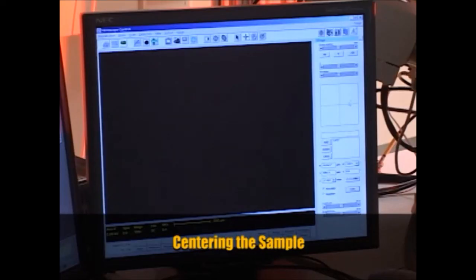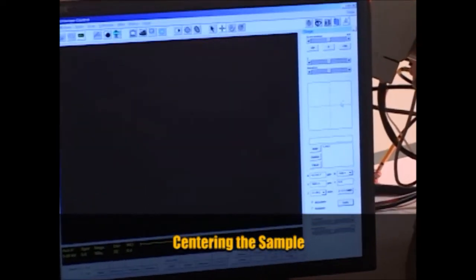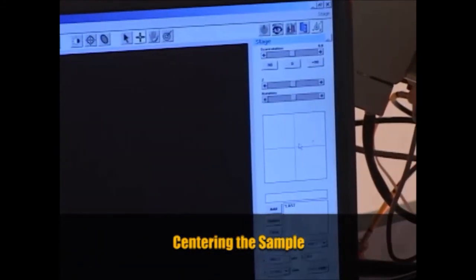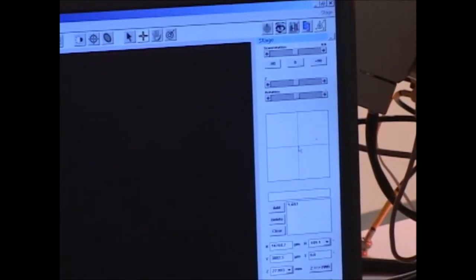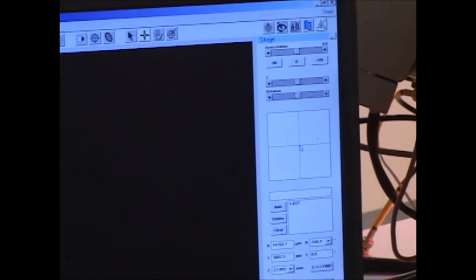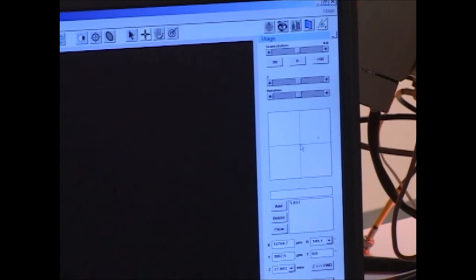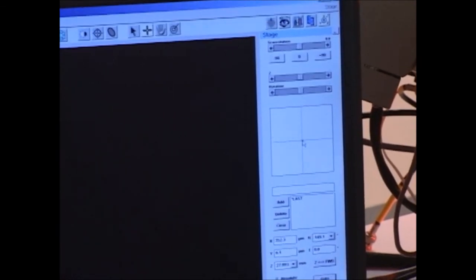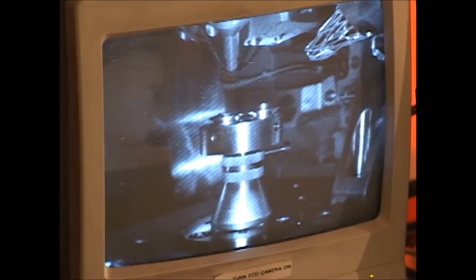Open the stage submenu, and that brings up a small map of where my sample is located. The X on this map indicates the center position where the beam is actually coming out. In order to recenter the sample, I'm just going to left double click at the center of the crosshairs, and you'll see the sample move to the center position on the CCD monitor.